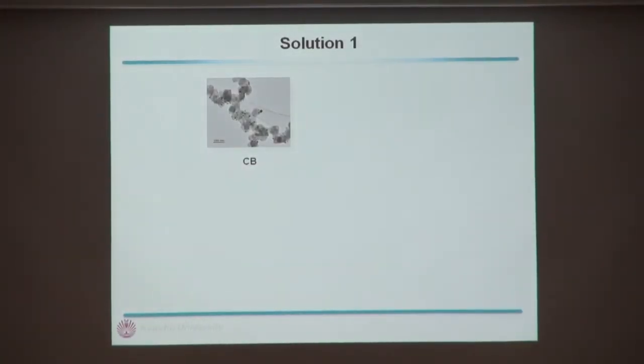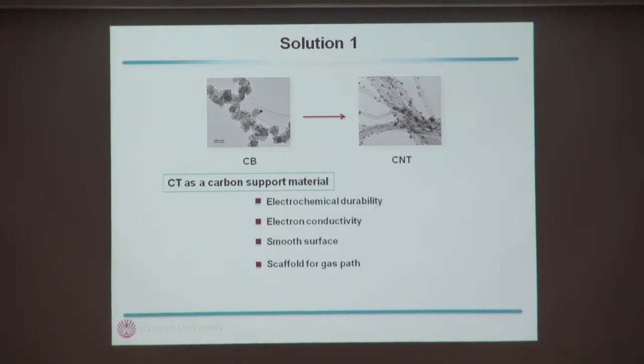So to solve the problem, we replace carbon black with carbon nanotubes. Because carbon nanotubes are electrochemically very durable, and their electron conductivity is very high, and their structure is very smooth, and such a structure may be useful as a scaffold for gas paths. So that's the reason why we replace carbon black with carbon nanotubes.